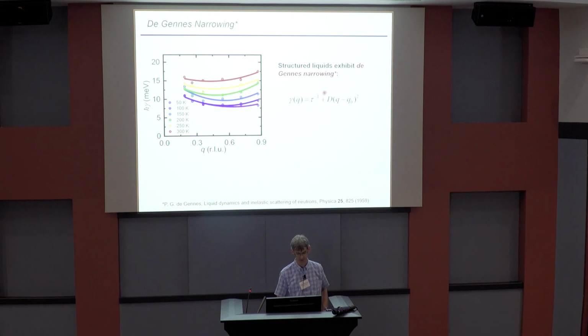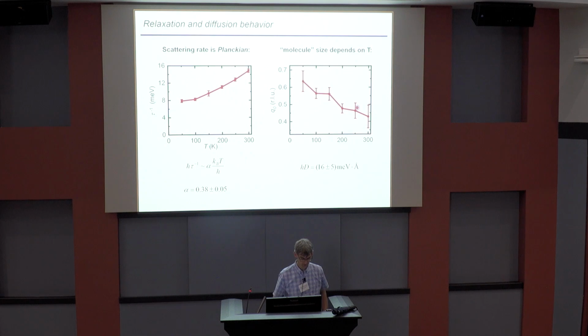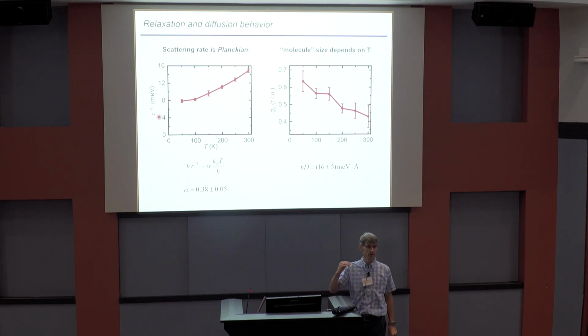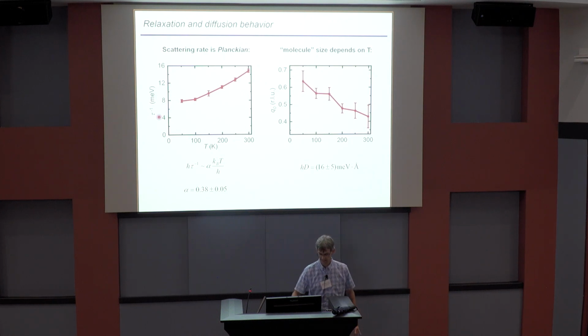So you can fit this thing, get a tau, which is sort of the momentum independent background, and then you can get a D and a Q. So D is the diffusion constant, Q is just the Q vector. And you can get the size of the objects, their diffusion constant, and then a background relaxation rate. And this is what they look like. So tau to the minus 1 is the Q independent part, so it's obviously a constant, but it is extremely temperature dependent. And at low Q, 8 meV is the resolution of the measurement, so it can never be less than that. It always eventually plateaus to some constant because we don't have infinitely good resolution.